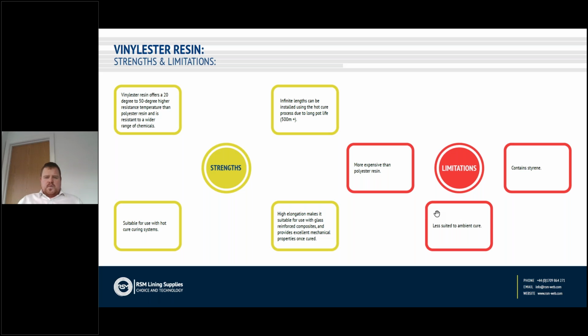In terms of a very quick overview of the strengths and limitations, we've discussed some of these already, but we can do very long length installations depending on the pressure required and the drainage system. Anything up to 500 meters is not beyond the realms of possibility if we have the right curing equipment. It's suitable for use with all heat and steam cured systems, has great elongation, as we've already mentioned, and a temperature resistance that's generally 20 to 50 degrees higher in combination with chemicals than standard polyester resin.